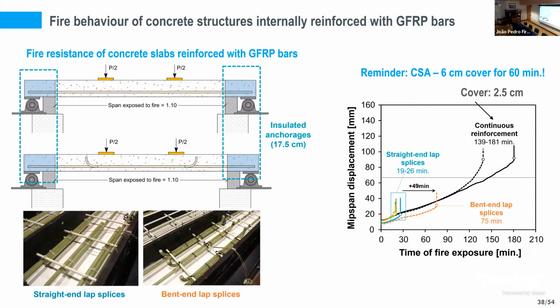We also investigated the influence of lap splices of the rebars, where we intentionally introduced lap splices in the fire exposed area to promote bond failure of the bars and to investigate the influence of that bond failure on the fire resistance of the overall member. We concluded that with straight lap splices, the fire resistance was, as expected, very low, below 30 minutes, but using bent end lap splices, we were able to extend the fire resistance quite significantly.